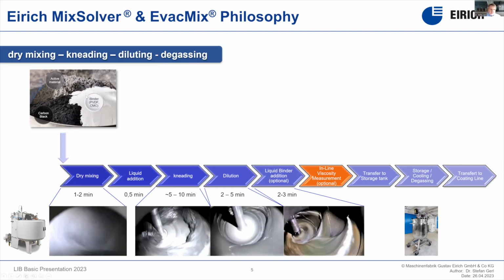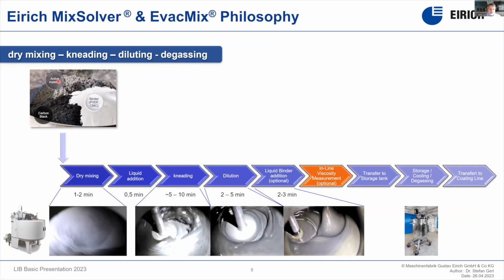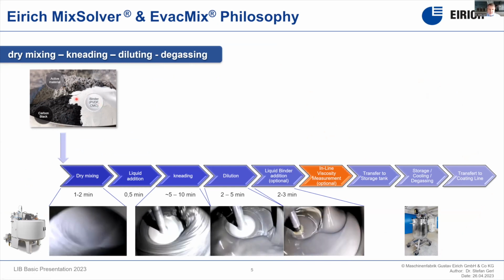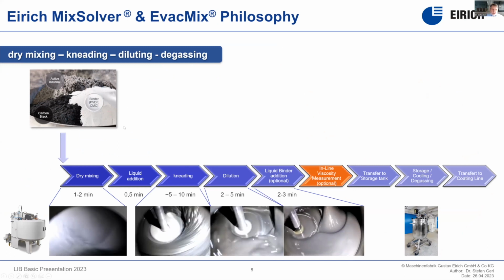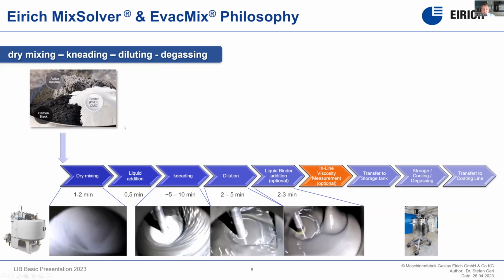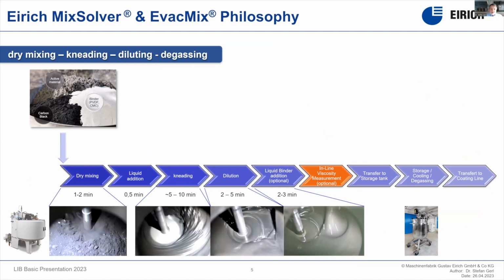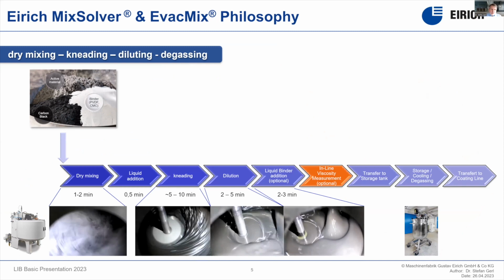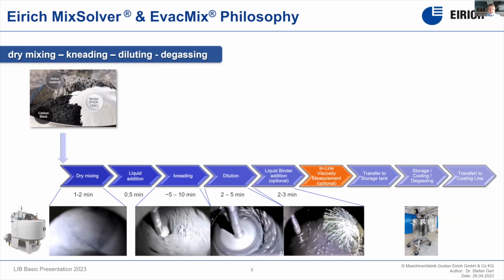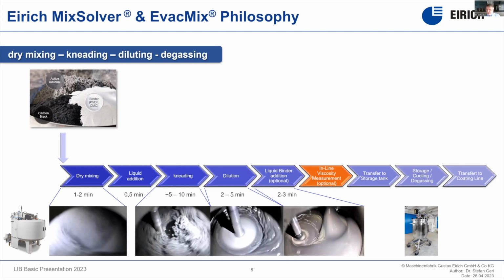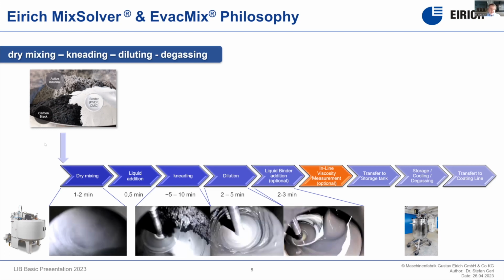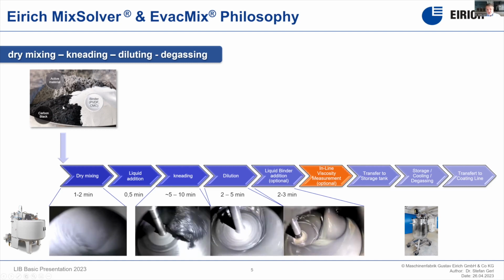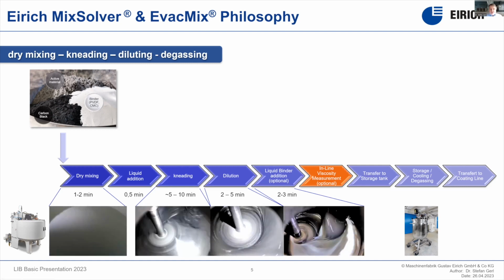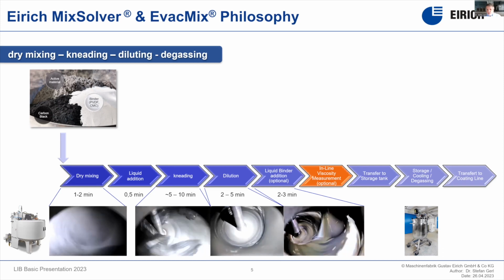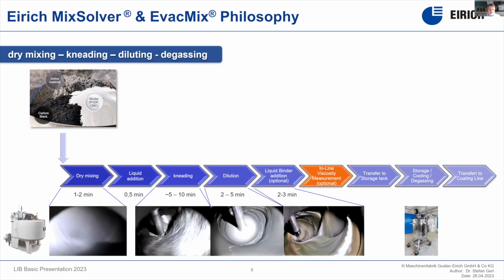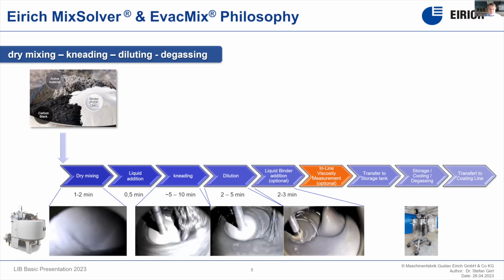So we said we add all dry materials, like the active material, the conductive parts, and the binder. We are doing an initial short, intense dry mix, typically 1 minute, to make sure, first of all, that all components are homogenized properly. The binder is separated from each other to prevent any jelly structures when adding the liquid. And we are dispersing already the carbon black to some extent. You will see later for the dry battery application, we run this a little bit more advanced. For the wet application, it's already good enough to run for 1 minute.